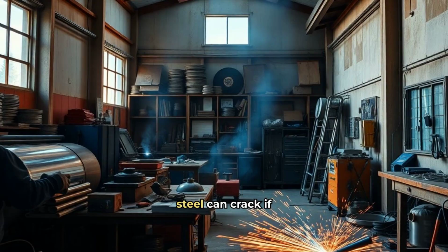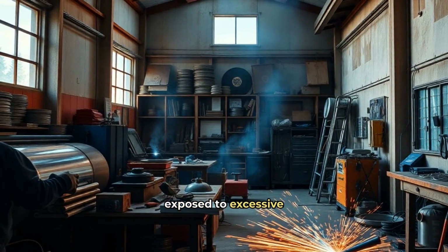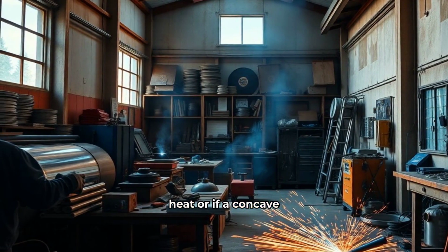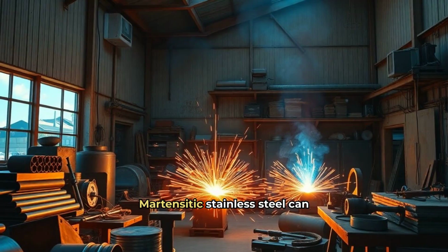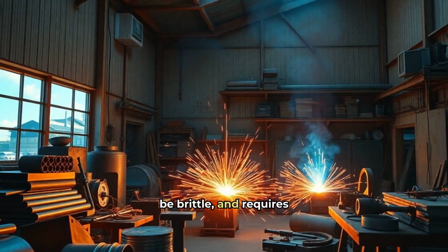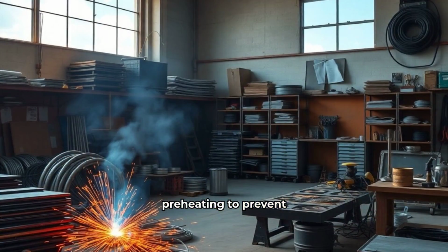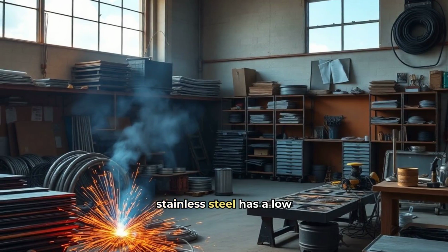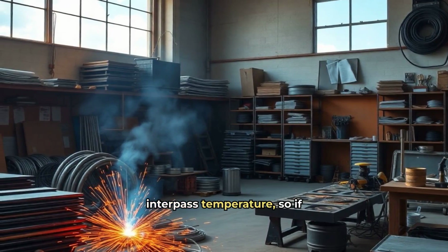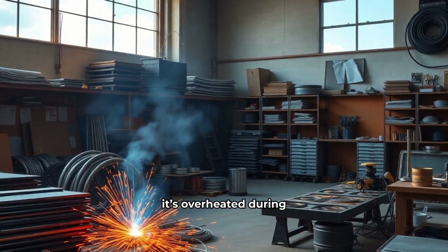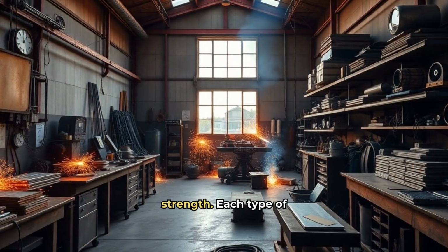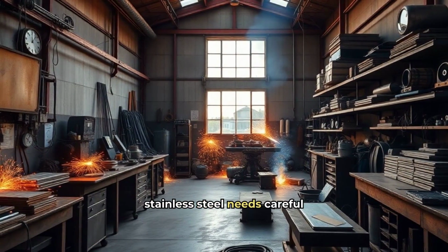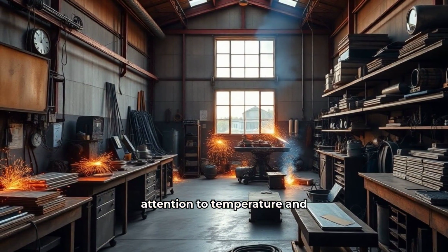Austenitic stainless steel can crack if exposed to excessive heat, or if a concave weld is made. Martensitic stainless steel can be brittle and requires preheating to prevent cracking. Ferritic stainless steel has a low interpass temperature, so if it's overheated during welding, it will lose strength. Each type of stainless steel needs careful attention to temperature and technique.